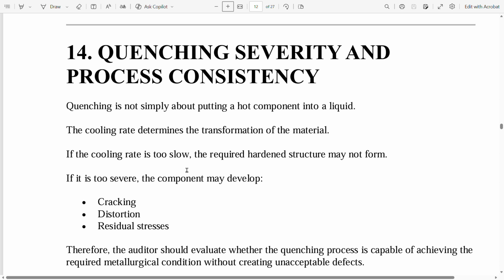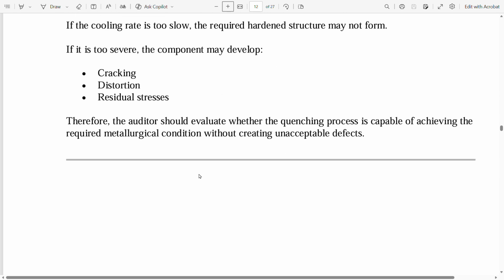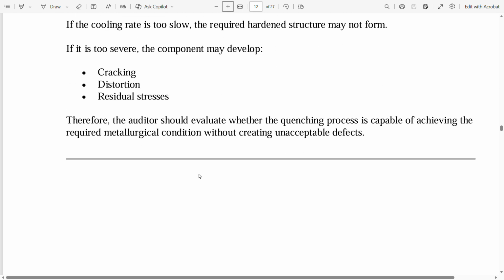Quenching is not simply about putting a hot component into a liquid. The cooling rate determines the transformation of the material. If the cooling rate is too slow, the required hardened structure may not form. If it is too severe, the component may develop cracking, distortion, residual stresses. Therefore, the auditor should evaluate whether the quenching process is capable of achieving the required metallurgical condition without creating unacceptable defects.